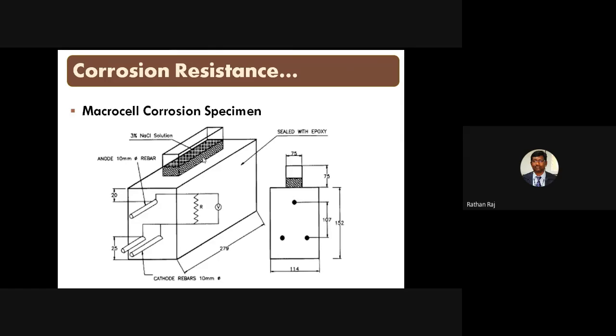the concrete. At the top, there is one container which is fixed and sealed using some sealant, and then sodium chloride solution is allowed to stay inside the container. After some period of time, 15 days or sometimes 30 days, the chloride content present in the sodium chloride is absorbed by the concrete, reaches the anode, and affects the passive layer on the steel. In this way, the macro cell corrosion test is done.